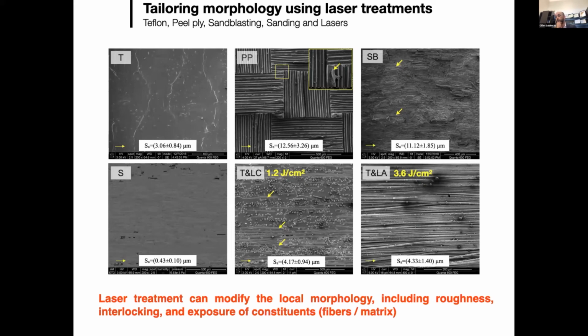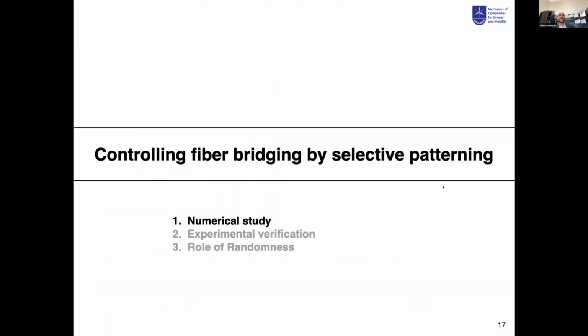So what is important to understand is that using laser, you can relatively easily control a pattern in terms of chemical properties of the surface, functionalization of the surface, and in terms of morphology and geometry of the surface. So you can really use your laser as a way to introduce patterns. Why is introducing patterns important? Because you can make a very simple numerical study at the beginning to understand the effect of heterogeneities on the propagation of cracks during a delamination.